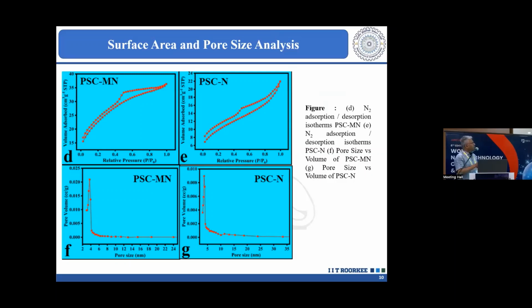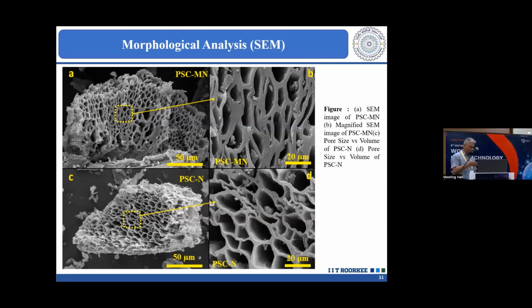Now, some of the test results are shown. Since it is a porous carbon, porous carbon has to have a large surface area. So in order to measure the surface area, BET surface analysis was done. This shows the relative pressure versus the adsorbed nitrogen, and then pore size versus the pore volume of two materials. Please, I again point it out: one material has both magnesium oxide and sodium chloride present, a templated material. Another material is devoid of magnesium oxide, with only sodium chloride present. So these are the two different types of hard carbon based materials that were tested.